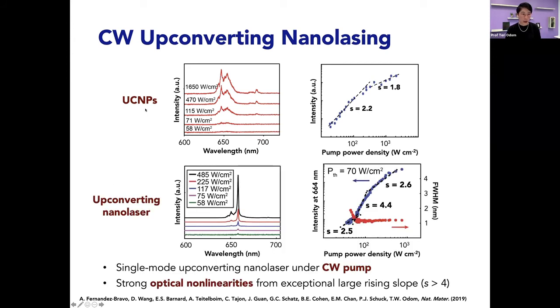And so if we evaluate these upconversion nanoparticles on the lattice, you can see, unlike the case where you just have the upconversion nanoparticles alone, as you increase the pump power, you have selective increase of one of these modes. And moreover, this is a single mode upconversion under a continuous wave pump, so it's not pulsed, it's continuous wave. And then if you look at the log plot, you can see, okay, we have a little over a 2 photon process, and then it becomes very nonlinear during the lasing regime, and then it tapers off just a little bit.